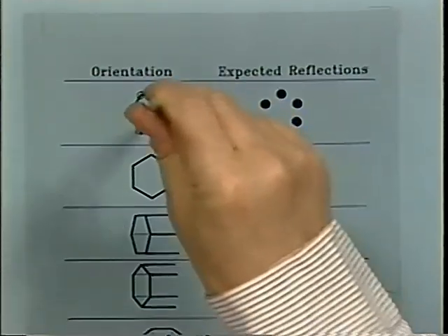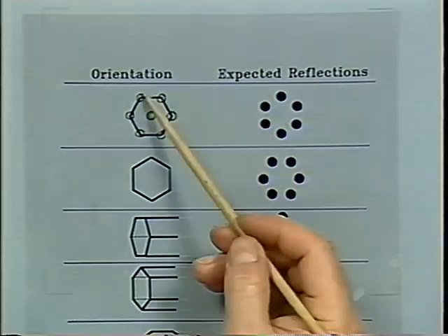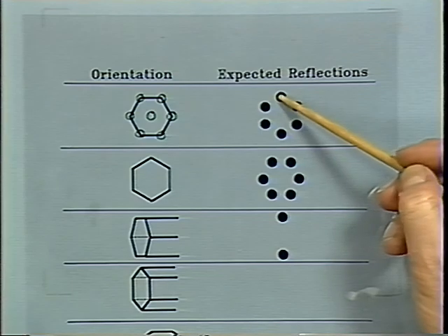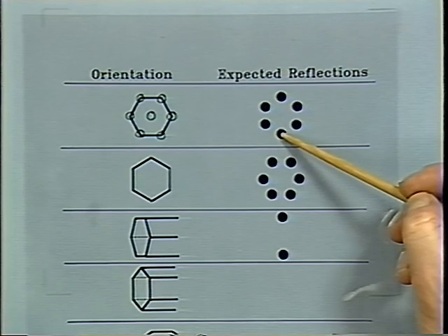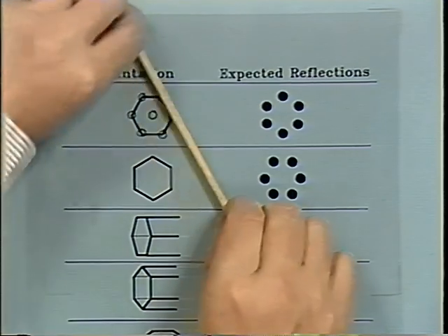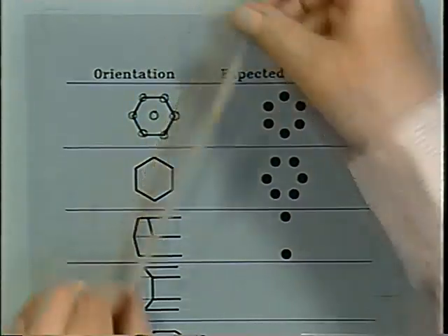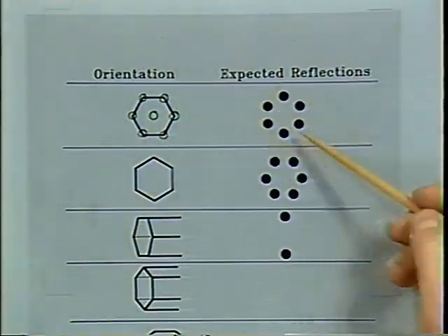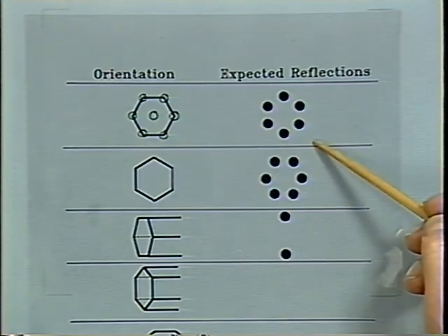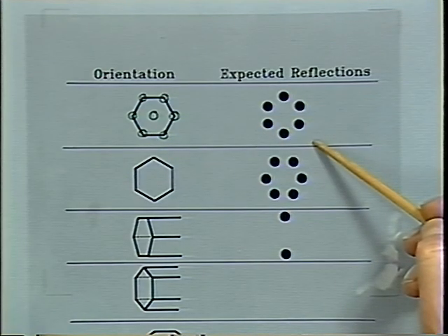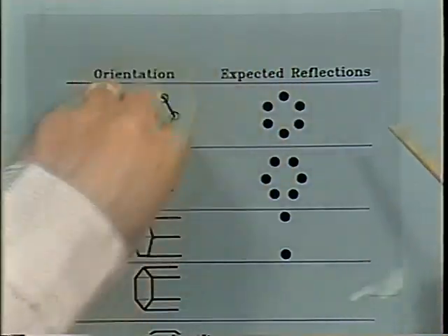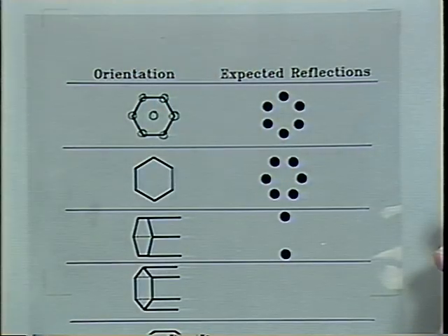The innermost reflection for the structure, which you just saw, in a light beam going down the hexagon, will give us reflections here from this plane, just a reflection up, reflection below. And from these other planes, you will get accordingly this reflection, and from those planes, you will get this type of reflection. So from this regular structure, you get 6 reflections, and the pattern is just rotated by half that lattice angle.